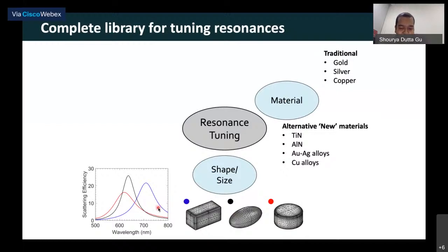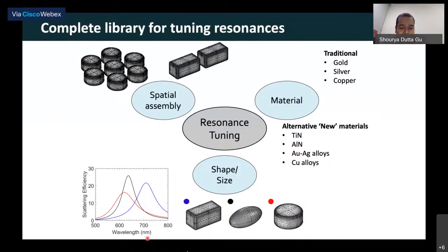For example, these are the three shapes that I'm taking here: a cuboid, an ellipsoid, and a cylinder. This is the scattering that comes from these three different structures. This is the wavelength and this is the scattering intensity. We see that they show three different resonance peak positions, so you can control it in this manner. Now, the third way is, why only single particles? You can start assembling these particles into different arrays. For example, this is a 7-particle array, and this is basically a dimer where you have two cuboids. So these are simple ways that allow you to tune the resonance of the plasmonic structure. This is basically a major part of plasmonics, that you want to tune the resonance so that it's optimized for your particular application.